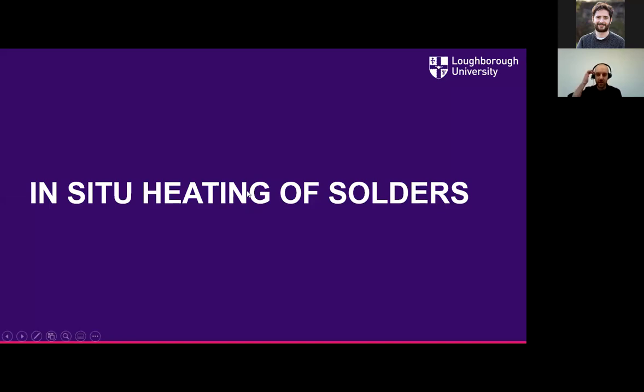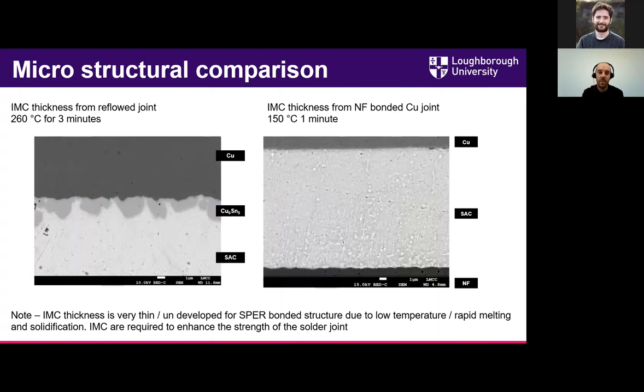So next we'll look at how we continue this work doing some in situ heating of solders, so essentially thermal aging. One of the research groups at Loughborough is doing self-propagating exothermic reaction bonding. So essentially they have a little foil layer which you can ignite, it heats up and causes a solder to melt and solidify very, very quickly. And this allows you to bond samples like the one on the right hand side without forming any intermetallic compounds because the heating and cooling time is so quick.